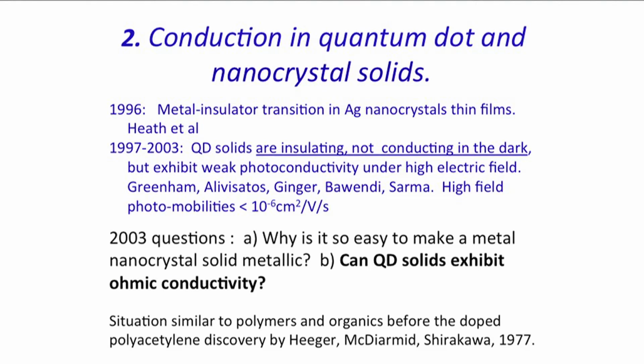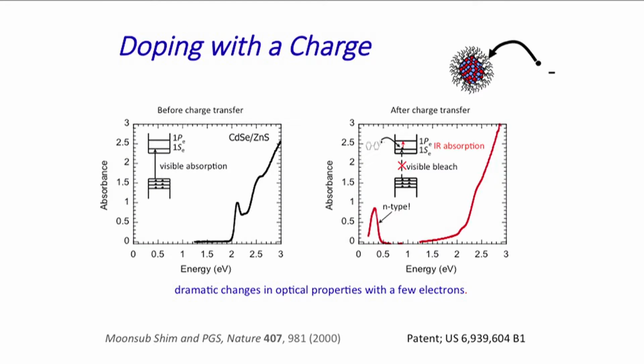And so in 2003, we were asking ourselves and the rest of the community, why is it easy to make a metal nanocrystal solid metallic, but quantum dots difficult? And so we addressed this issue with doping. The first thing you need to do if you want to have a solid that's conductive is to know what its Fermi level is. That's basic solid-state physics, and so we knew that. The only question was, how do we change the Fermi level? Well, you change the Fermi level by putting charges in or taking charges out. And so that first challenge was how to dope it.